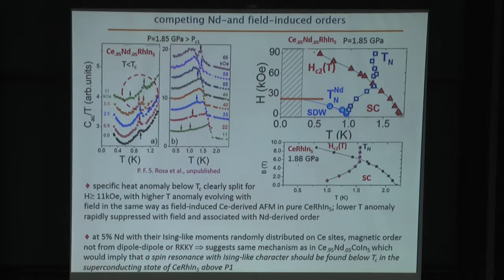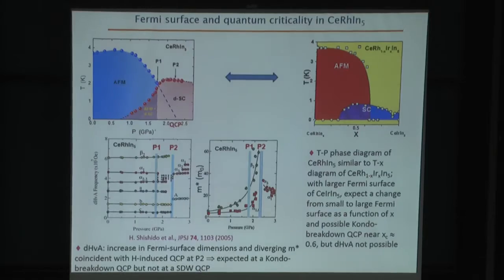So again, if that interpretation is correct, then there should be a spin resonance develop in the superconducting state of even pure cerium rhodium indium 5 at pressures above where there is no long-range magnetic order. Of course, this will be a very difficult experiment, but it should be an important test of our interpretation.